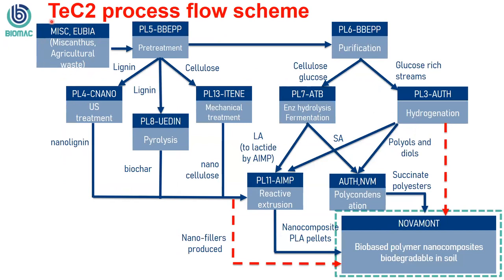So you can see once more, we have agricultural waste here, miscanthus, being converted as a biomass source and pre-treated and purified. And so we have many different streams here. We have pre-treatment to produce lignin that is then being converted to nanolignin, the one additive that I mentioned previously that potentially gives you some, for instance, antioxidant or stabilization properties. We have another stream where the lignin is being converted via pyrolysis to biochar. So again, this is what gives us this deep color. And we have another stream that converts cellulose to nanocellulose, which is then allowing us to enhance the mechanical characteristics of these materials.